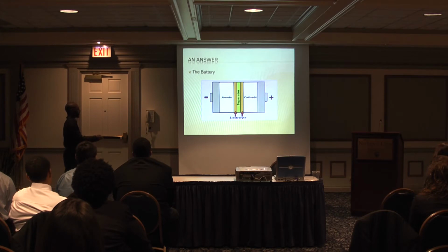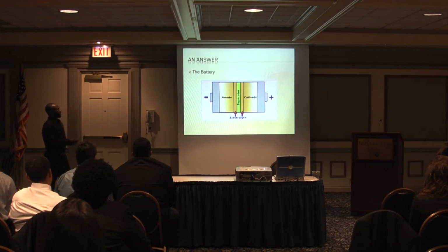The electrolyte then seeps into the pores of both of our electrodes, and what you can see are little bits of white space. That white space represents areas that have not been touched by our electrolyte. The electrolyte is significant because the lithium ions can only move through the polymer separator if the electrolyte is touching a lithium ion. Any lithium ions that exist in these white areas cannot move across the polymer separator. That's energy that can't be used.